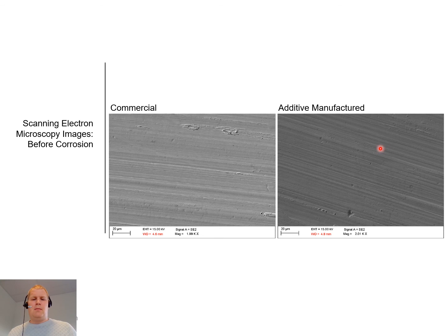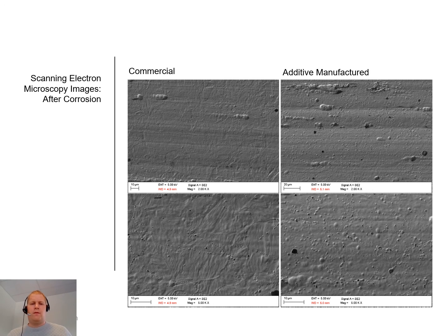Here you can see the SEM images of the samples before the corrosion test, with the parameters applied on the SEM instrument depicted here. As you can clearly see, except for a few imperfections here and there, the samples are relatively smooth. Here you can see the SEM images of the samples after the corrosion test, and you can clearly see more damage to the surface. Numerous black dots, which are basically tiny holes in the surface, can clearly be seen. They are known as corrosion pits. You can also clearly see that there are many more of them on the additive manufactured sample compared to the commercial sample. This fits well with the observation that the additive manufactured sample has corroded more than the commercial sample.